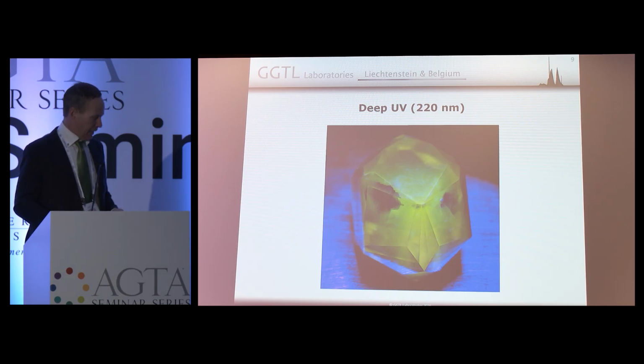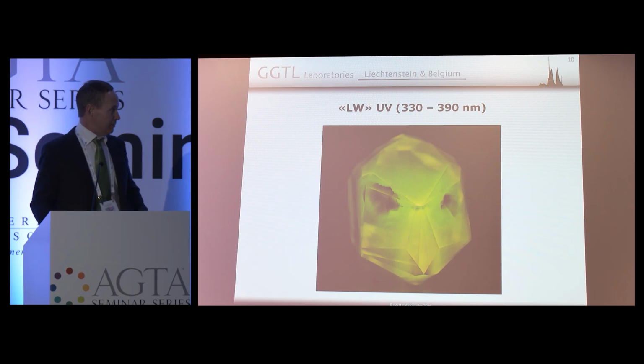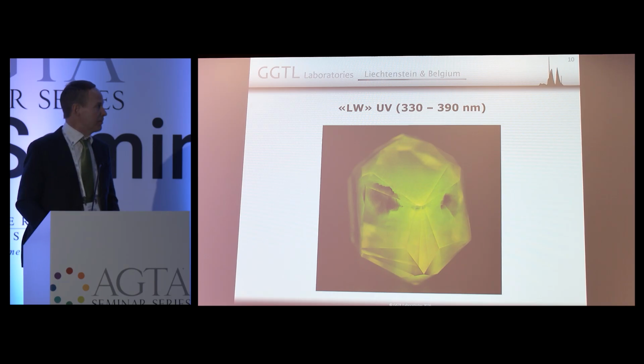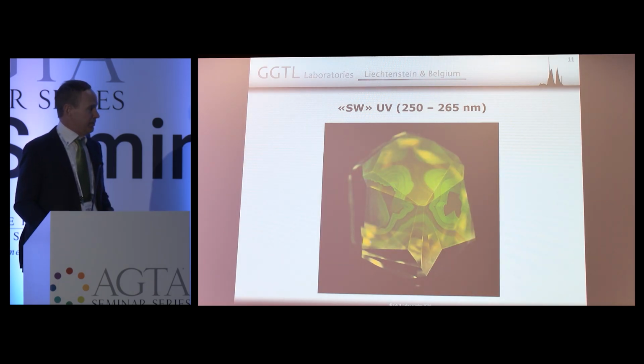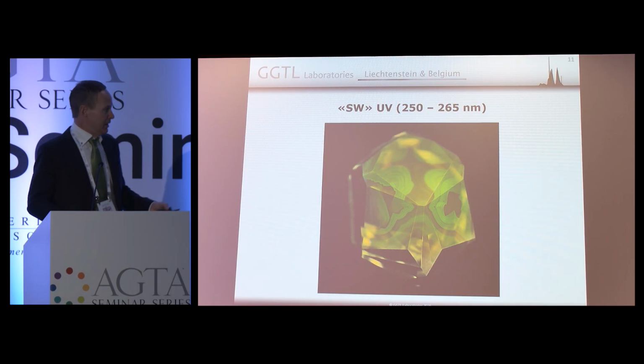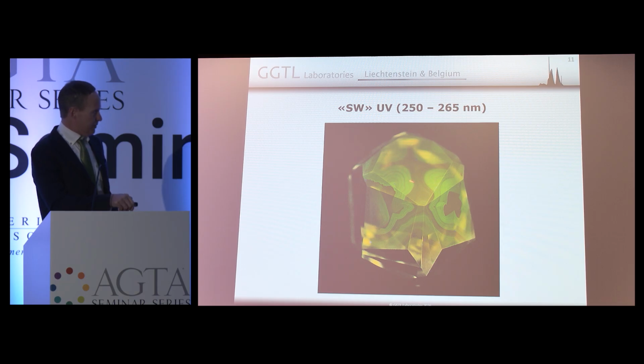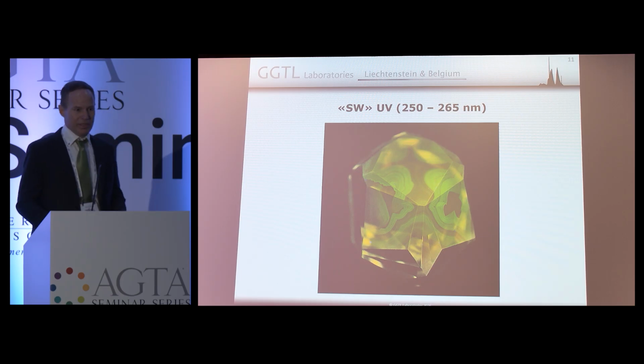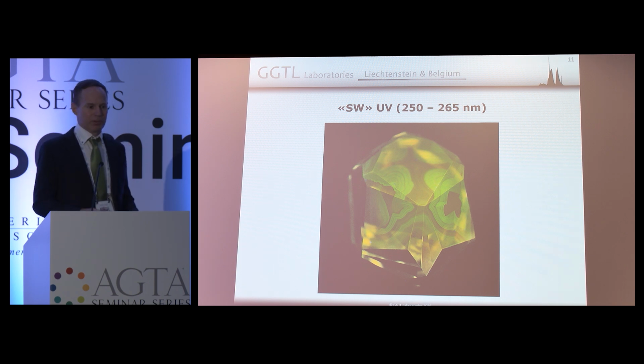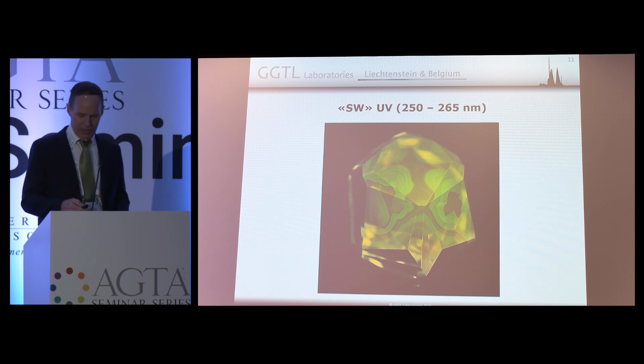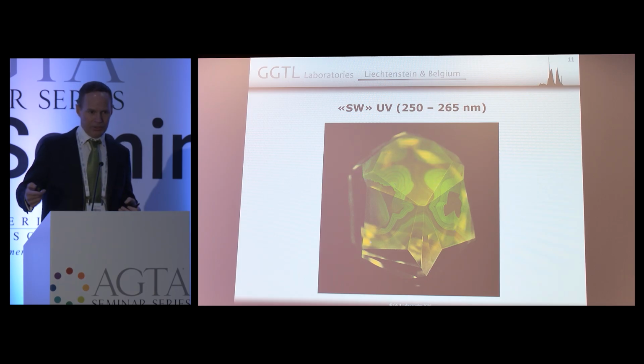Now let's look at the stone at long wave UV, basically. So we're seeing almost the same. Still not very spectacular. And now let's go into shortwave, and there we are. So you're seeing all the growth that becomes visible that before was invisible at 260 nanometers. There it is. And depending on what diamond you're testing, one excitation may be way better than the other, and you can't always predict which one it will be. That's why we have developed this system where we can, by joystick, switch wavelength in milliseconds.